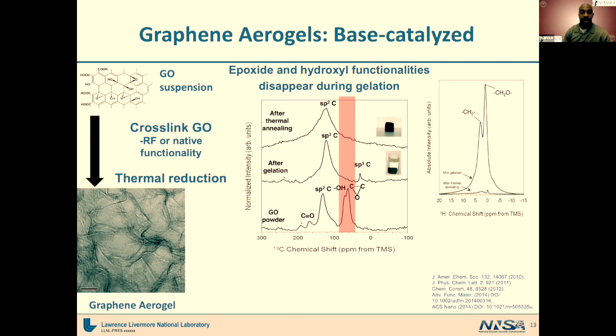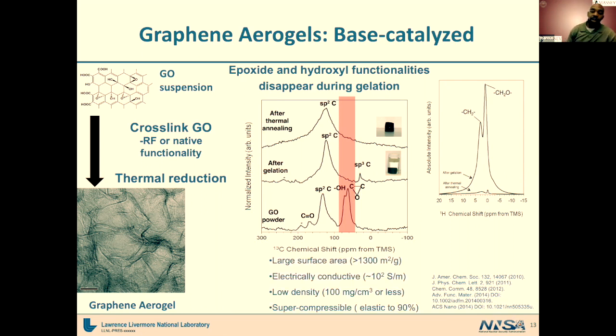And so if you now look at the morphology of this particular carbon gel or graphene aerogel, you would see that you have more of this sheet-like morphology that you would expect from a gel that has constituents that consisted mainly of graphene oxide or graphene, now that you remove the oxygen functionality. And then if you looked at the properties, you're able to see very large surface areas, good electrical conductivity. You can get to very low densities. And in this case, these materials are actually very compressible as well.